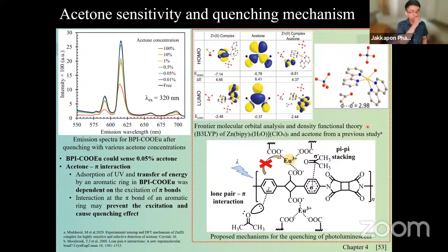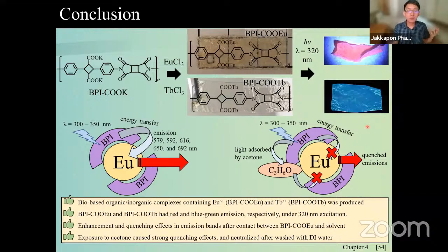Now, as I said, we created a photoluminescent BPI with europium and with terbium, and with the ligands. When you have the UV, it's going to transfer the energy into the lanthanide, and it's going to give a very big emission. But the acetone will just block it, and it cannot transfer the energy. That's why you have a quenched emission here. So here is the mechanism that I'm trying to explain.